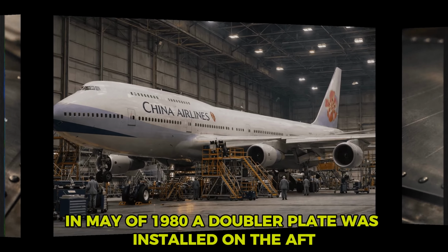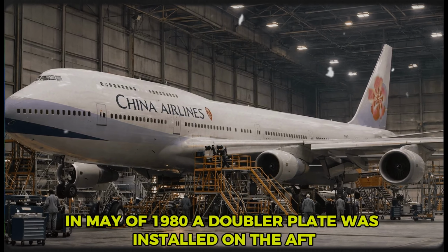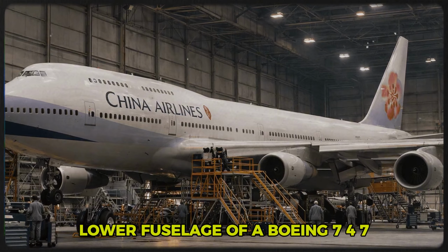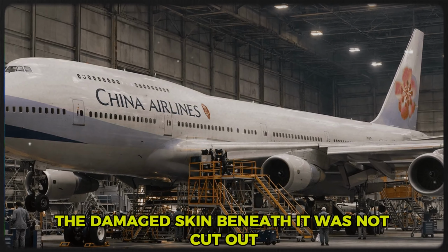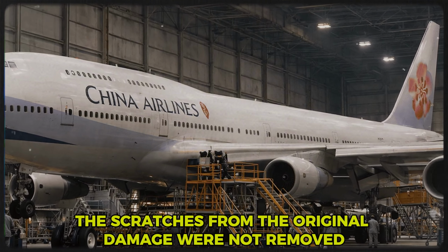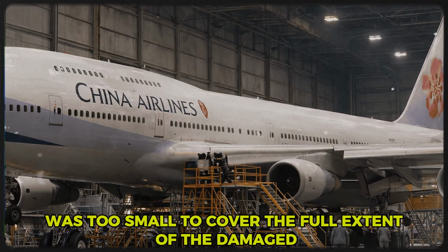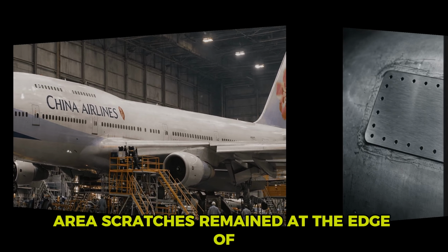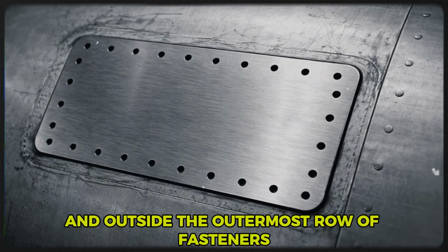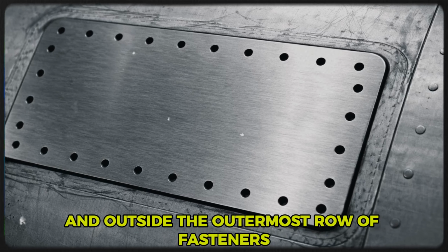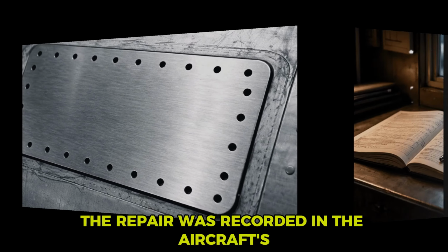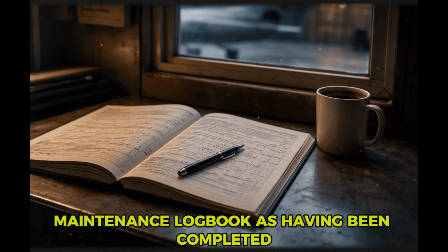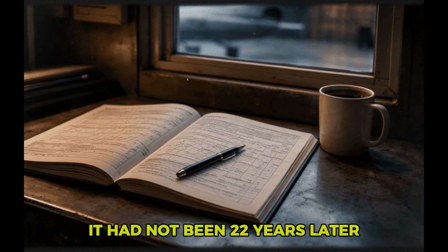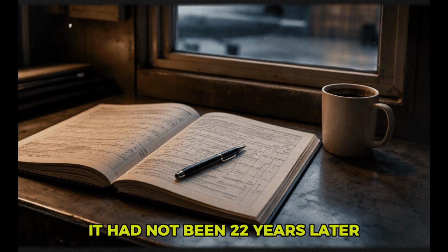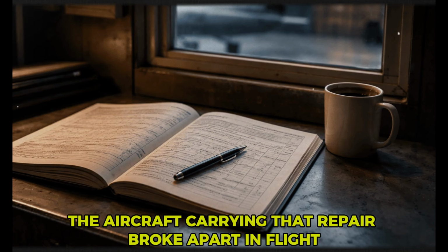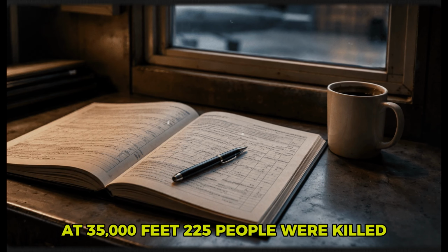In May of 1980, a doubler plate was installed on the aft lower fuselage of a Boeing 747. The damaged skin beneath it was not cut out. The scratches from the original damage were not removed. The doubler was too small to cover the full extent of the damaged area. Scratches remained at the edge of, and outside, the outermost row of fasteners. The repair was recorded in the aircraft's maintenance logbook as having been completed in accordance with Boeing standards. It had not been. 22 years later, the aircraft carrying that repair broke apart in flight at 35,000 feet.